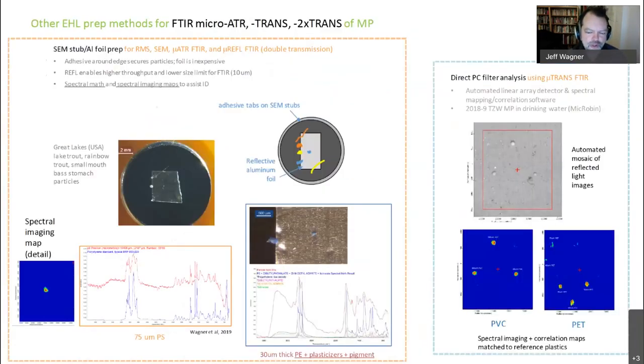I wanted to mention a few other preparation techniques that we use. I should have mentioned in the previous slide, all those were contact mode, FTIR, ATR mode, which we still prefer for the biggest microplastic particles, but for smaller ones, we have a couple different techniques for doing microtransmission or reflectance, which in our case is essentially double transmission since you're passing it through the particle, hitting a reflective surface, and passing it through the particle again.